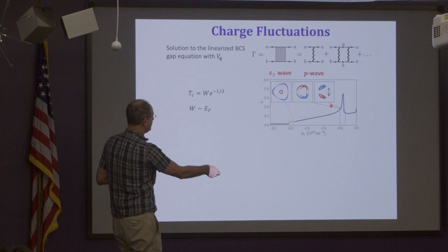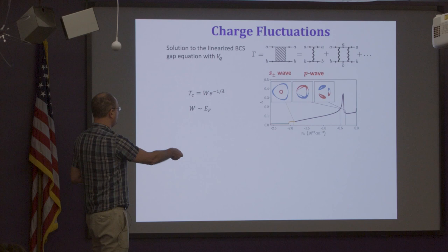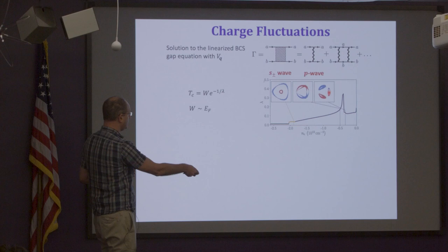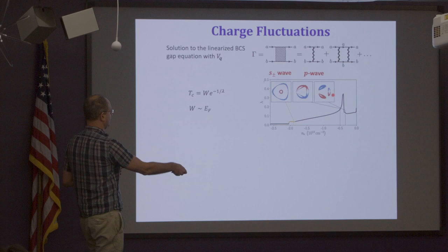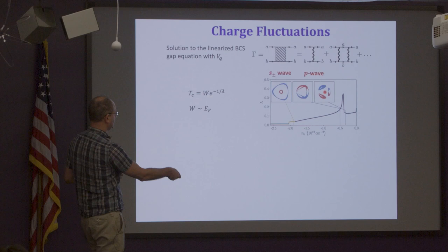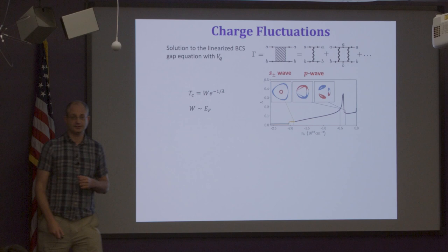You see this very large, very sharp peak in lambda. That's the Van Hove singularity, when we go from an annulus to three disconnected pockets. Our theory would break down somewhere here. Of course, that's the best place for superconductivity, but at some point we would have to do something else. So we should cut off our calculation somewhere, maybe here. You see that the annulus is not essential. The superconductivity persists, and it's actually quite strong within this calculation, even in the region where we have three pockets. And the symmetry of the order parameter is the same.